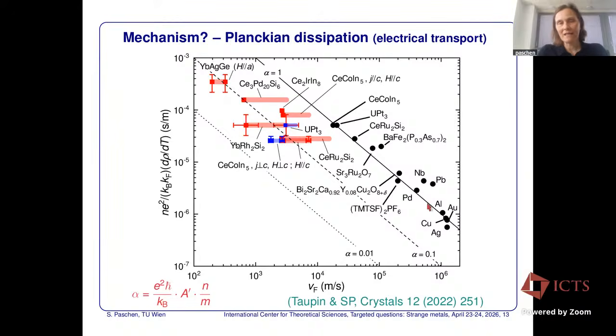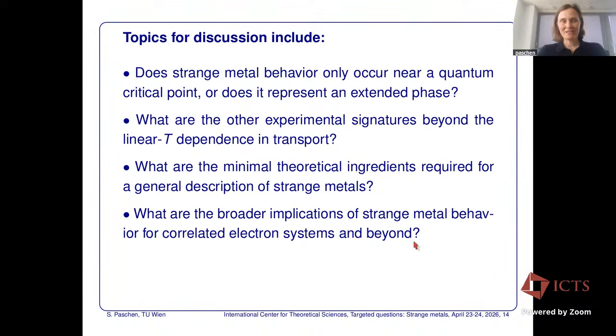We reinvestigate heavy fermions with transport to extract the coefficients that we need in addition to the A prime. And we see that the closer we get to the quantum critical point, this is always the closest point to the quantum critical point, the lower that alpha would be. So that means to us, if we at least take the systems that are close to the quantum critical point, there is no must to claim Planckian scattering with alpha equal 1. So that's the questions that we had up, and I will focus on this one.